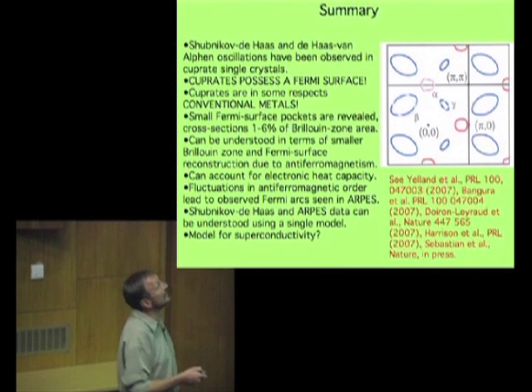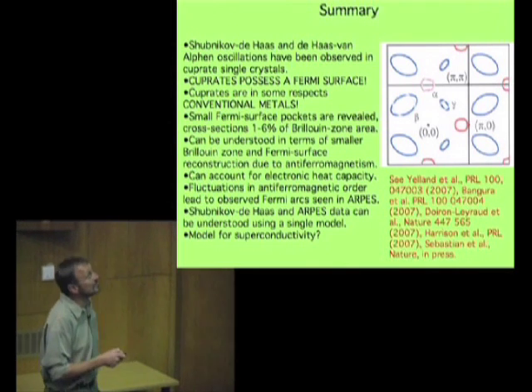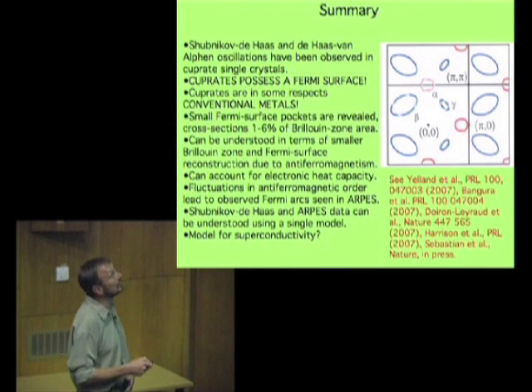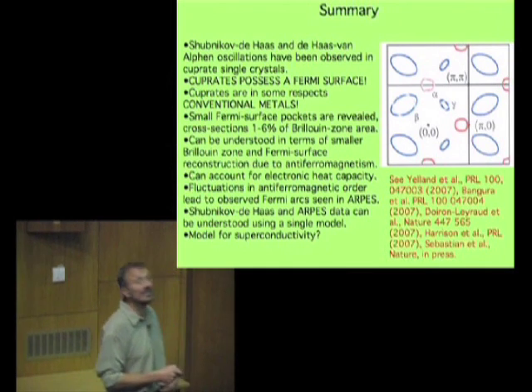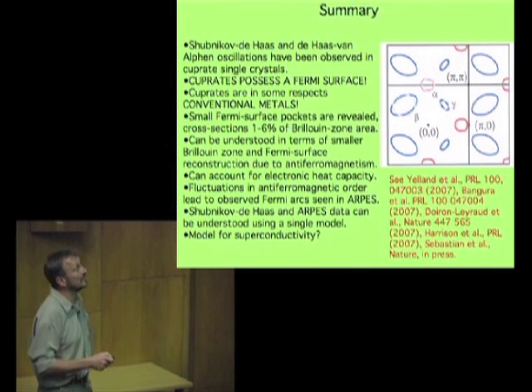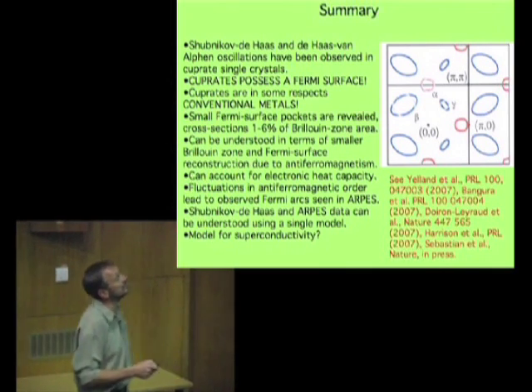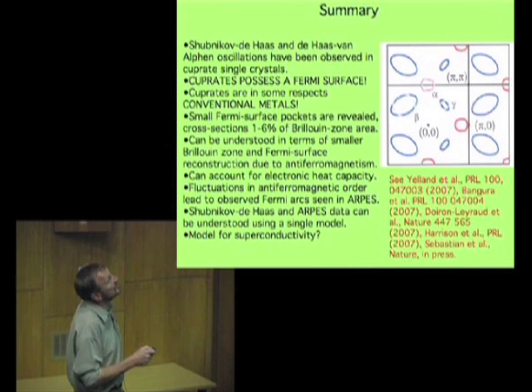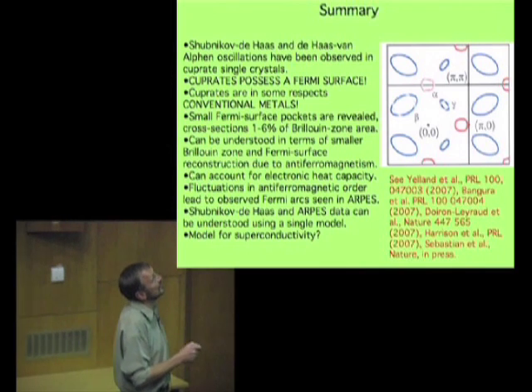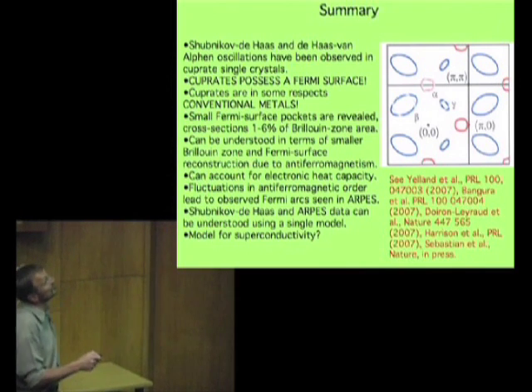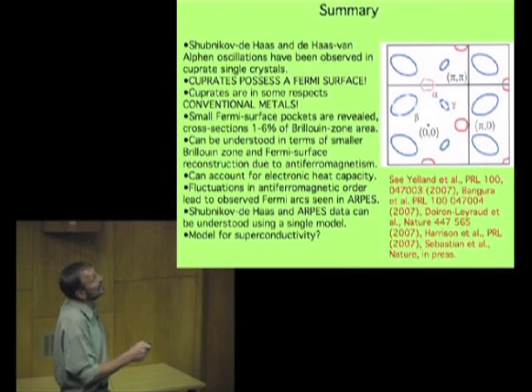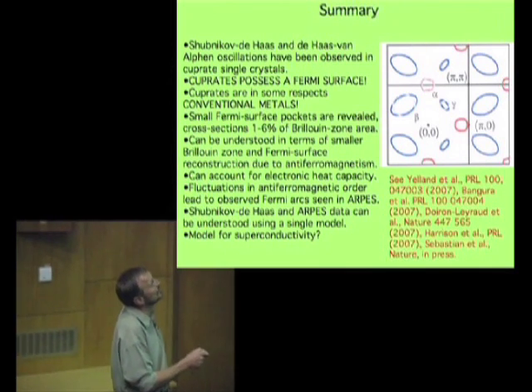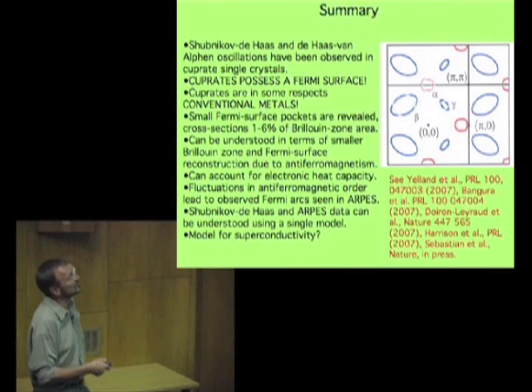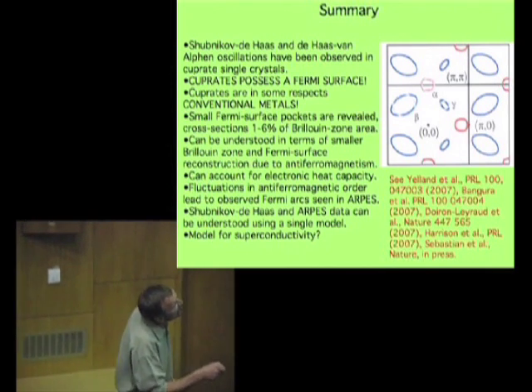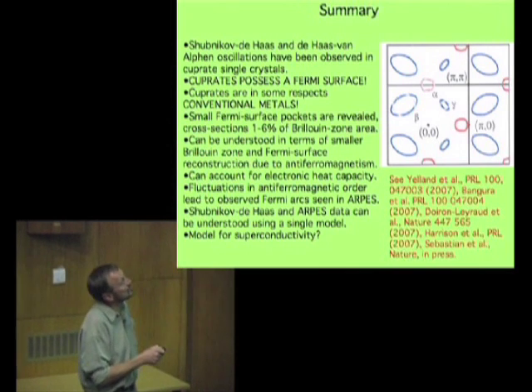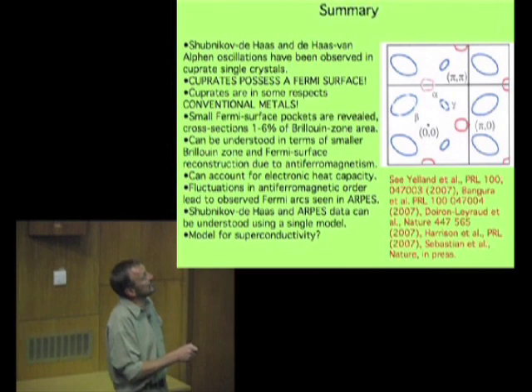So in summary, I think that measuring the Fermi surface has opened up a whole lot of opportunities in these cuprate materials after about 20 years of relatively stalled theoretical comprehension. We've observed Shubnikov-de Haas and de Haas-van Alphen oscillations in cuprate single crystals. Because we've observed these oscillations, it means that cuprates possess a Fermi surface. Cuprates are, in many respects, like conventional metals. We see these small Fermi surface pockets, with areas that are 1 to 6% of the Brillouin zone area.